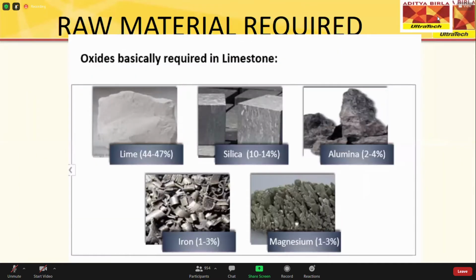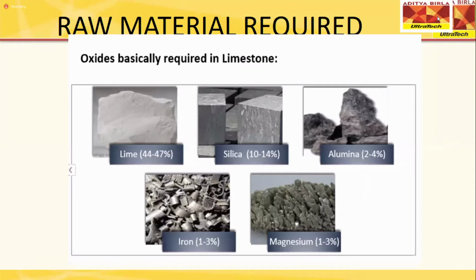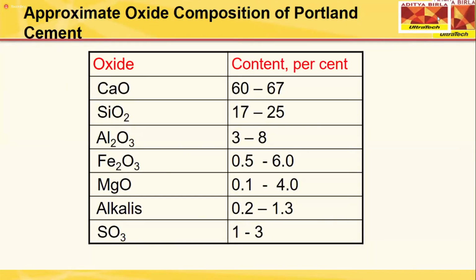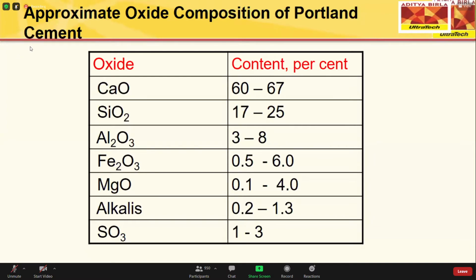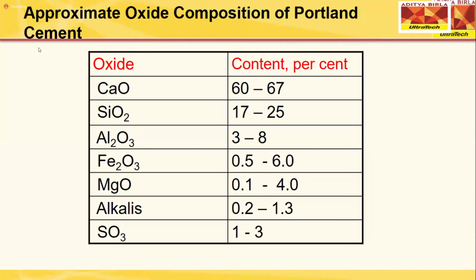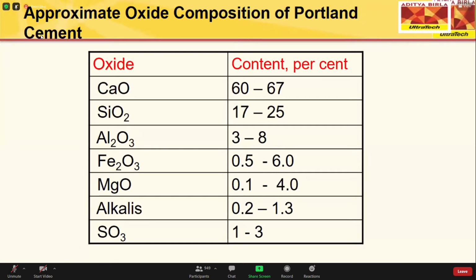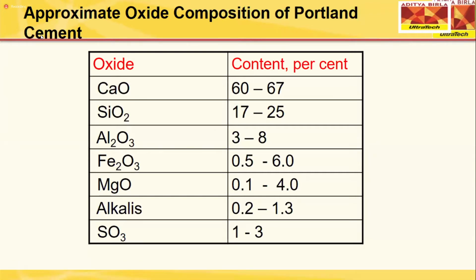Yeah, next slide. So from the calcareous raw material, we get lime, calcium oxide, and from the argillaceous raw material, we get silica, alumina, iron, and magnesium. Next. So from these various raw materials, the oxides which are required for producing cement are calcium oxide, silicon oxide, aluminum oxide, ferric oxide, magnesium oxide, alkalis, and SO3. Now these oxides, when they are heated to a temperature of 1450 degrees centigrade, they get fused to each other. The reactions take place, and we get 4 important compounds which are a core part of the cement.